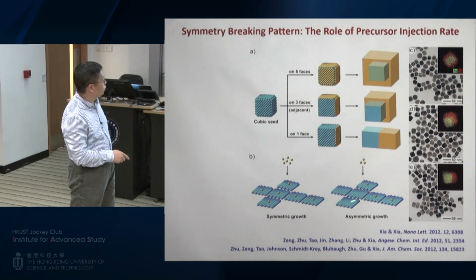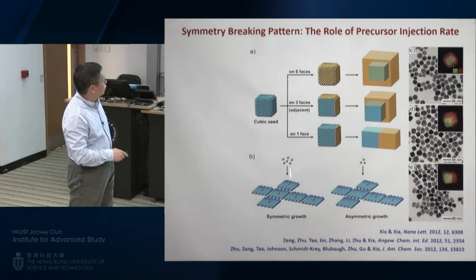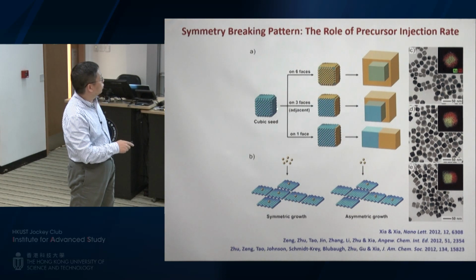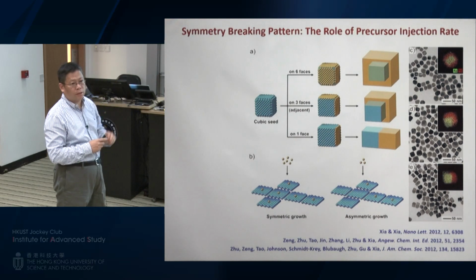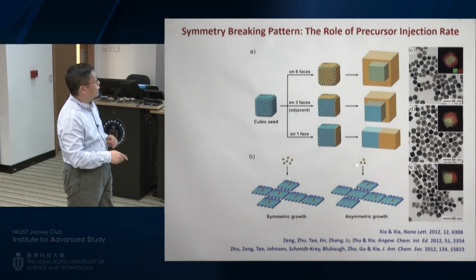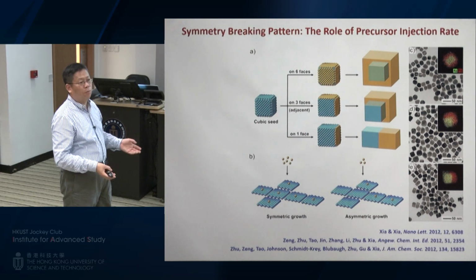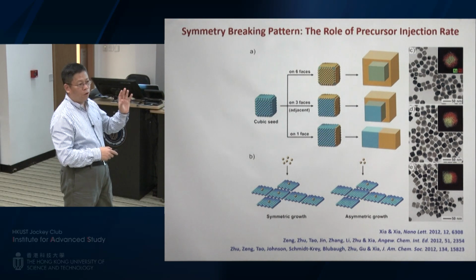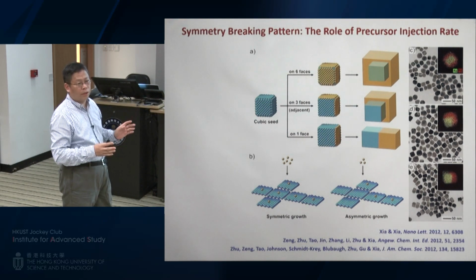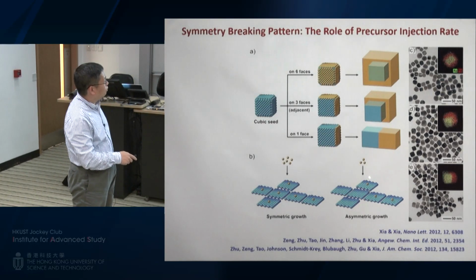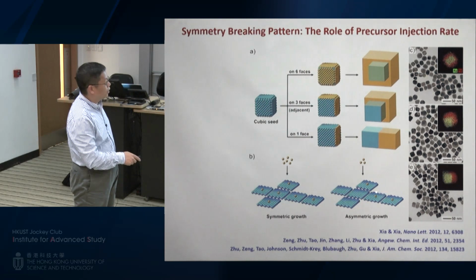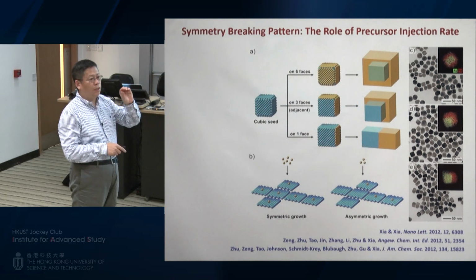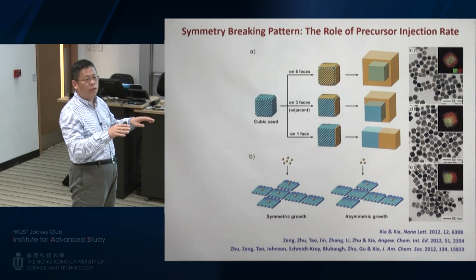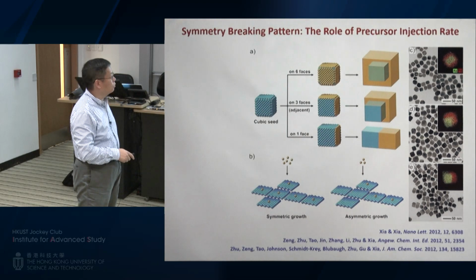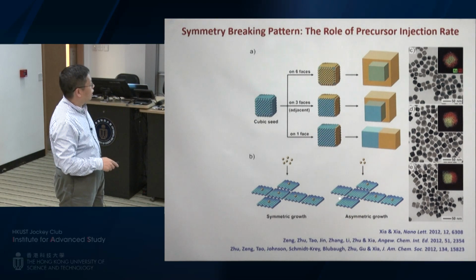So I used this cartoon to show the idea. For example, for this cubic seed, growth is going to be initiated on the side faces. We have 6 side faces, right? So now if you only generate like 3 atoms, the growth, of course, cannot be initiated from all the 6 faces. It's just impossible, right? If you have 6 kids, you only have 3 candies. You can only give candies to 3 of the kids, not all of them. Okay, that's just impossible. So in this case, maximally you can only have 3 of the side faces receive the atoms for the initial growth. So this is going to be the stage of symmetry breaking. Once the symmetry is broken, the growth will continue along this pattern. They're not going to change actually, okay? And that's basically the idea about symmetry breaking.